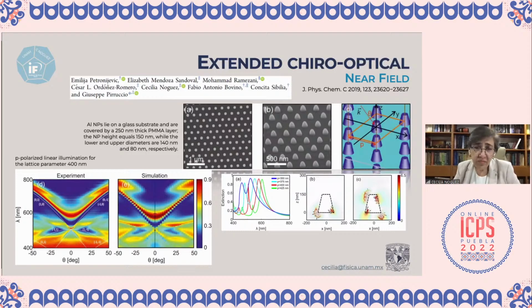Also, by looking at these nanoparticles, you can see that they form a triangular array, and it's very uniform. However, the shape of the nanoparticle is not symmetric. That means you have a truncated cone, so the base of this nanoparticle is wider than the top, and there is an asymmetry that gives rise to a quadrupolar response of the nanoparticle. So you can have a dipolar response, but also a quadrupolar response.